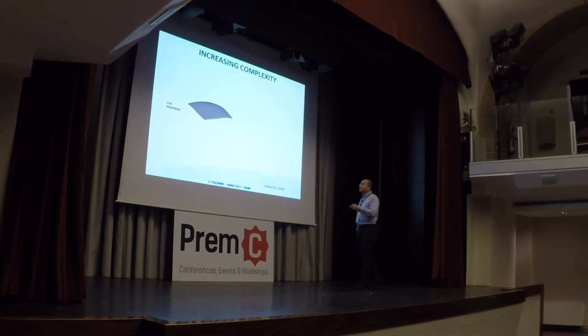What are we doing now? Well, you can use this approach of depositing and using the nice two-dimensional structure of graphene to do even more complex structures. First, we coated the metal foam not with graphene from solution, but we grew graphene directly on top by CVD. Then, of course, you can deposit your iron oxide on top, and maybe you can deposit other layers on top of it. So this can be useful, for example, to limit the detachment of this iron oxide.